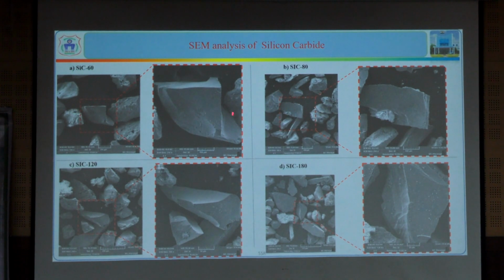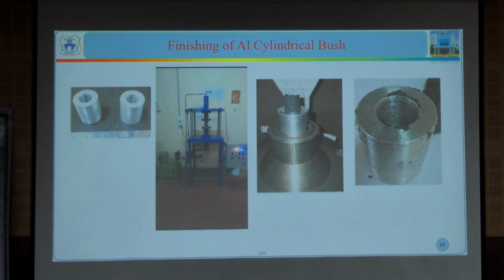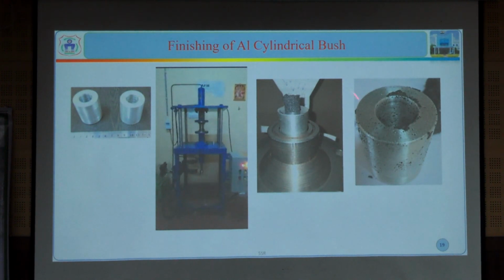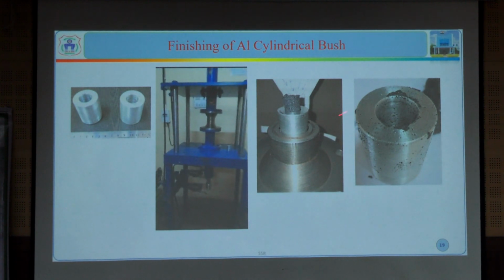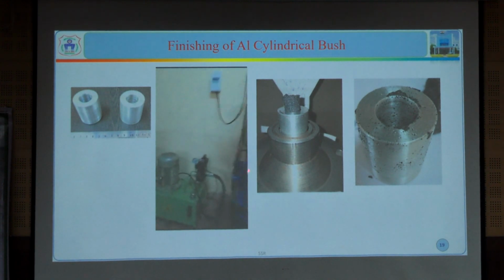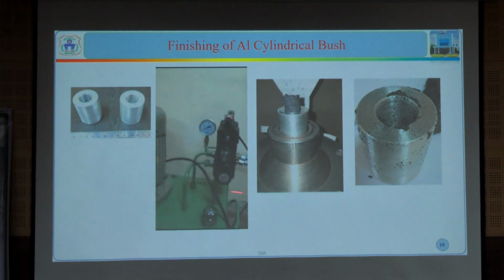And we use different grades of silicon carbide particles like 120 size, 80, 60, even 180 size, etc. Under the scanning electron microscope, we have identified the size of the particle, the size we are choosing, and also the shape of the particle we can identify. While pumping the media, we observed before and after finishing of the sample under the defined pressure,